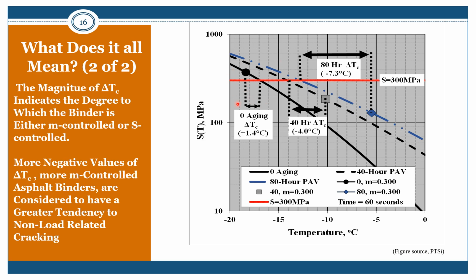In this figure, if you recall, the non-aged binder, zero aging, had a positive delta Tc of 1.4 degrees C. And then after 20 hours of aging, we had a 1.6. Well, here we look at 40 hours of aging, and you see now it's a minus 4 degrees C, versus 80 hours of aging, which we have a minus 7.3 degrees C. So you can see the effect of aging on the increase in the delta Tc.